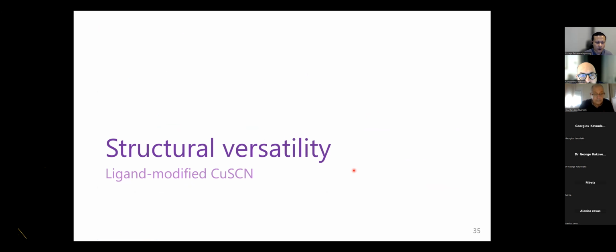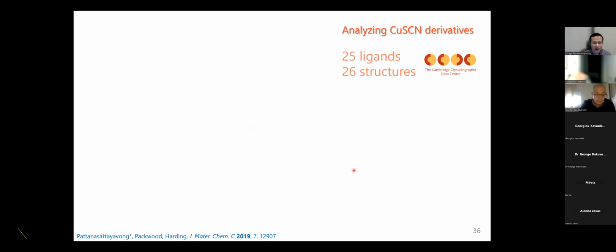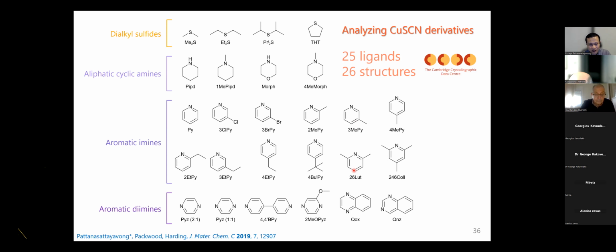Okay, what about beyond copper thiocyanate? So we see that the dialkyl sulfide molecules can coordinate directly with the copper thiocyanate and form a new structure. My background is actually physics, but from this work, we started to explore the chemistry side more, and we looked at what is available. From the structural chemistry in inorganic chemistry, people have already reported many structures of copper thiocyanate derivatives coordinated with ligands. And we compiled this and then did some DFT study.